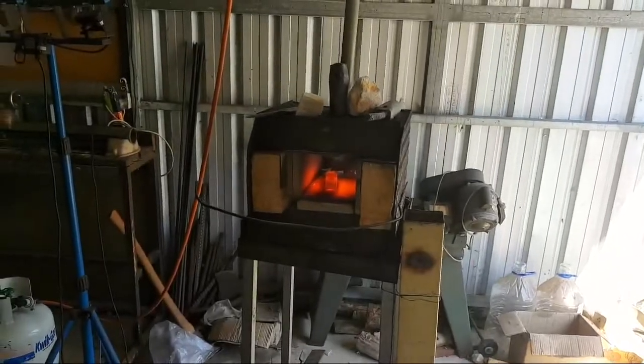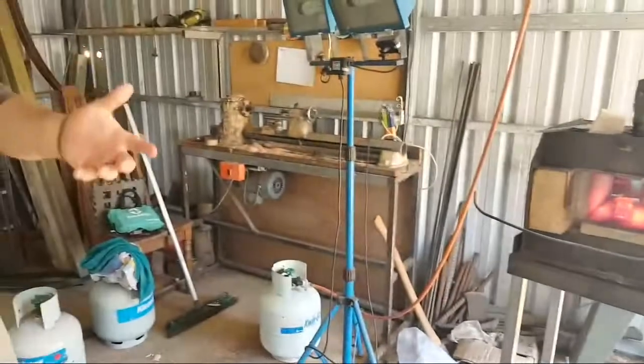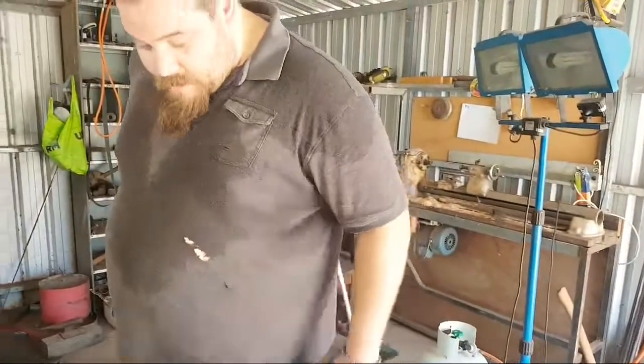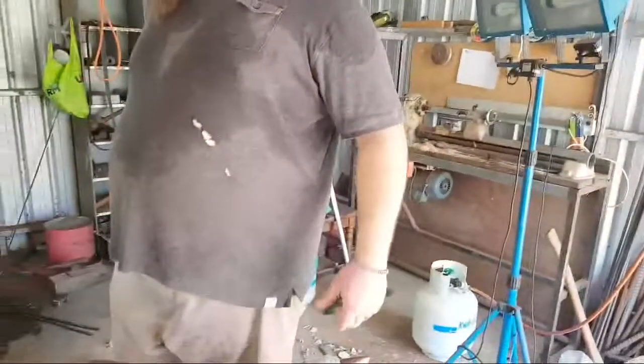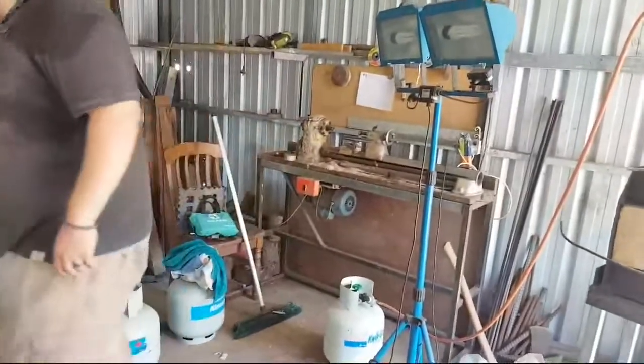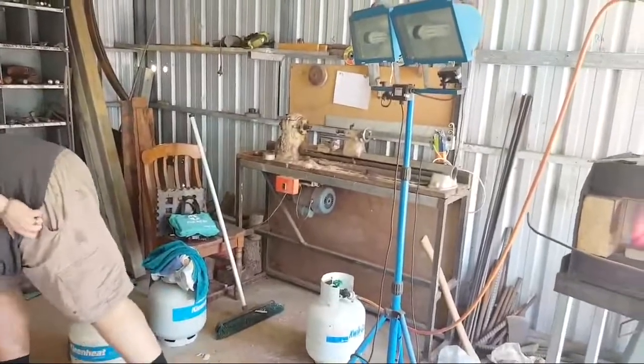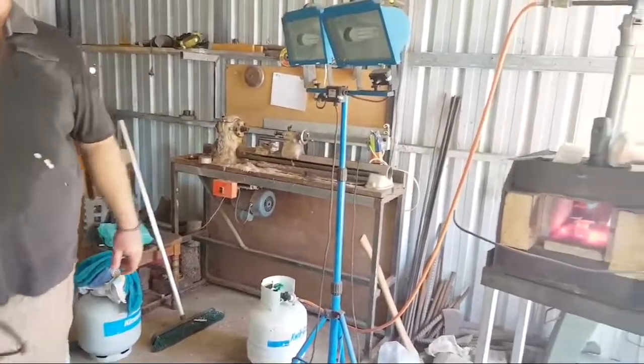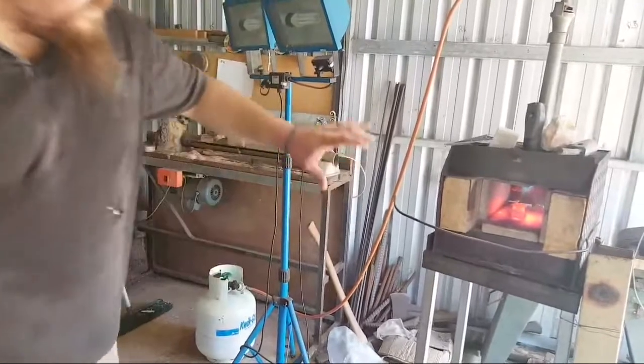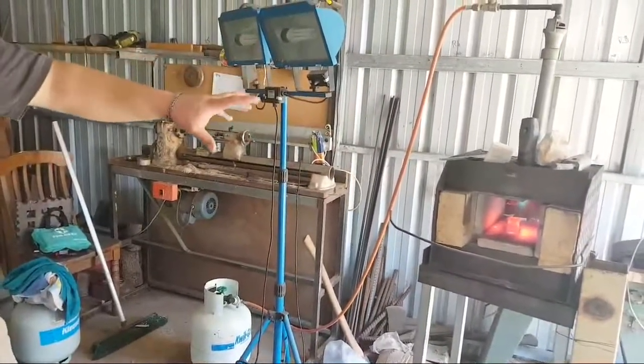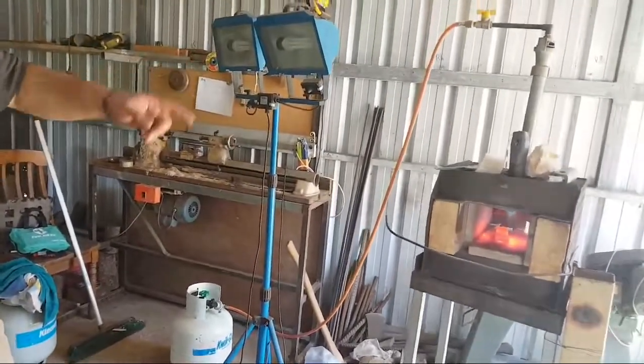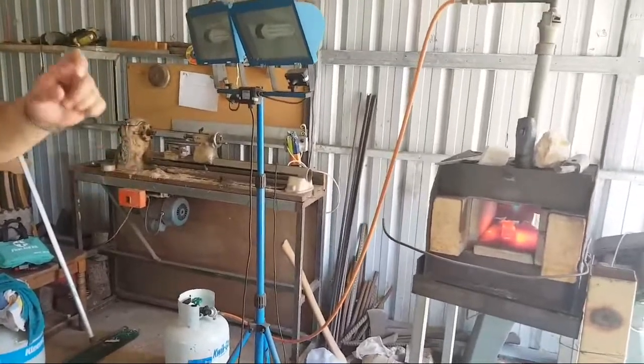The cheeks get up to heat faster than the rest of it because the cheeks are thinner. So you're always going to have hot cheeks and cold sides, which when you're heating in the gas forge you've got to be very careful of, because if you're not running around the right heat, then the cheeks will overheat. And you'll get increased grain growth in your cheeks, which means that there's more likely to crack the hammerhead in half. Oh, it's overheated.